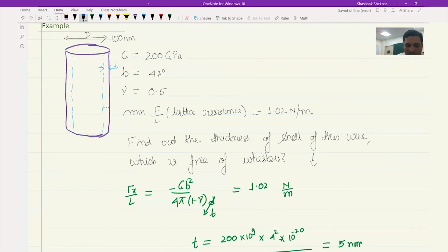And therefore, whatever is the minimum force required, it is equal to the force acting on the dislocation, and hence it can move. But what if some dislocations are oriented such that the glide plane is like this? In which case, this dislocation would be able to move from a much lower depth. So probably somewhere over here.